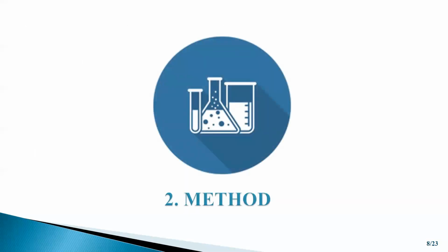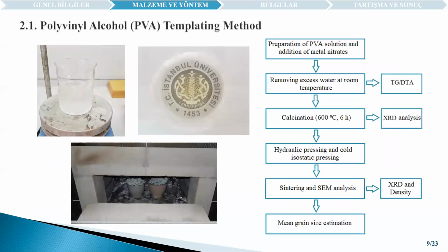Now I will try to explain our laboratory work. Studies show that polymeric materials such as cellulose, polyvinyl alcohol, and chitosan can be used as template in the production of porous materials. With the templating method, it is possible to synthesize ultrafine and pure powders. To produce ceria powders, first a 5% by weight PVA solution was prepared. Then stoichiometric amounts of metal nitrates, which are samarium nitrate and cerium nitrate, were dissolved in the PVA solution.